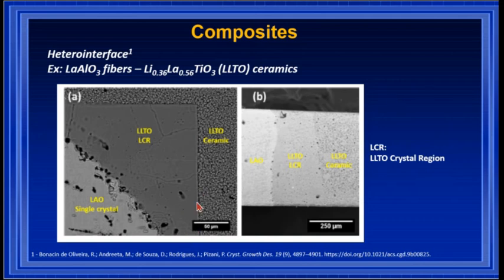We can see here again in a micrograph the crystals developed from the lanthanum aluminate fibers and the ceramic matrix. You have a very sharp interface here. When we cut the cross section, we can see the lanthanum aluminate interconnecting the electrodes, and the LLTO crystal region, which we call LCR, interconnecting as well the two regions without any grain boundaries here. And also the LLTO fibers with a lot of grain boundaries here, okay?